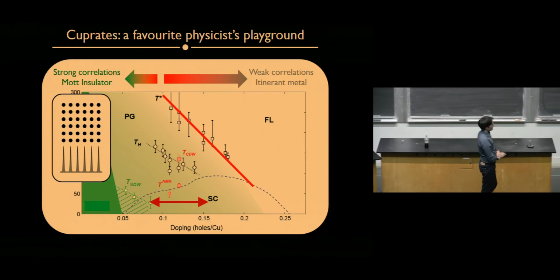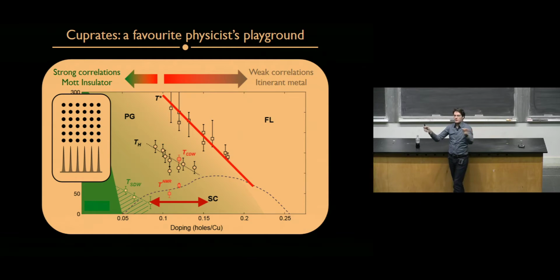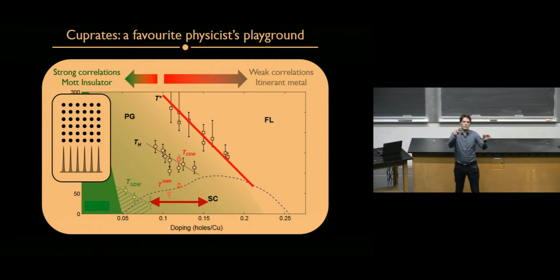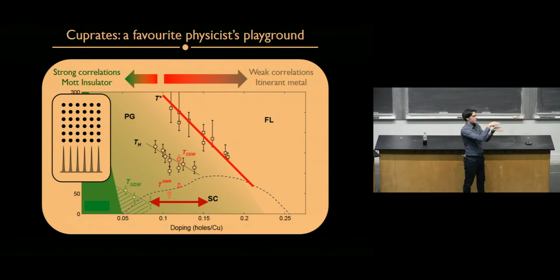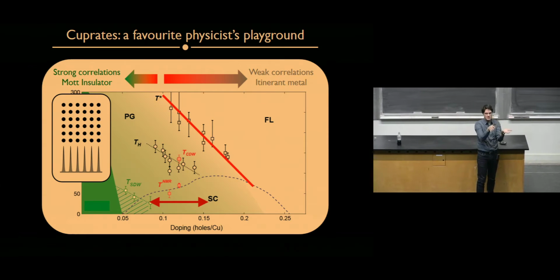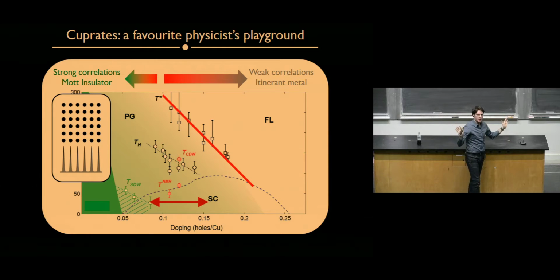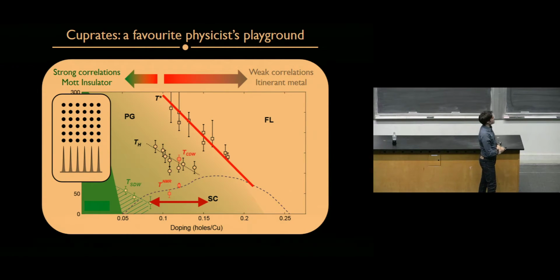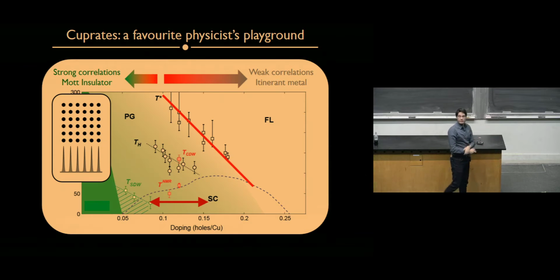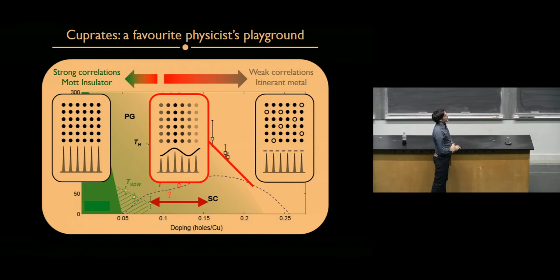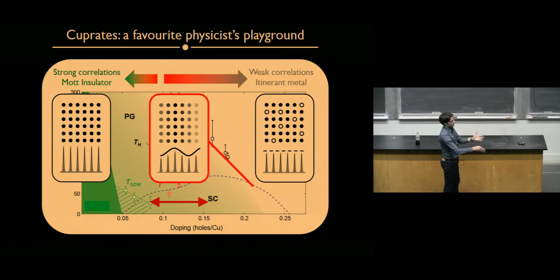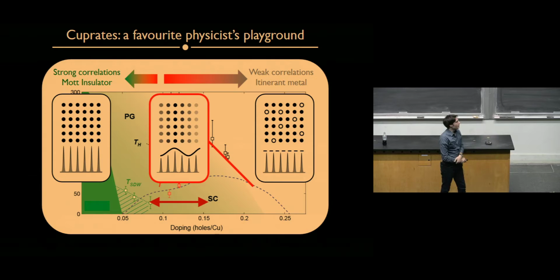This is a Mott insulator, which means that you have one electron per copper site. Electrons cannot move, because as soon as one electron moves to the neighboring site, then you have two electrons on the same site. The interactions are very strong. The energy of that configuration is very large, and that hopping process is effectively forbidden. So there is one electron per copper site, nothing happens. This is an insulating state. It's very well known, and it's a strongly correlated state of matter. On this end, you have doped a sufficient number of holes that they're free to move around in a liquid-like state. So you have a good conductor down here.